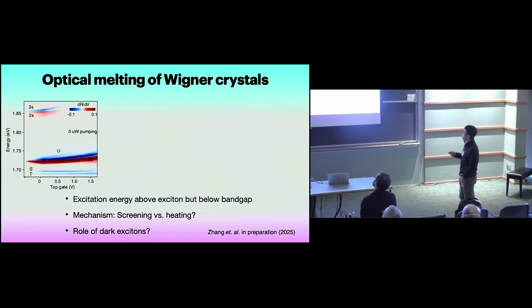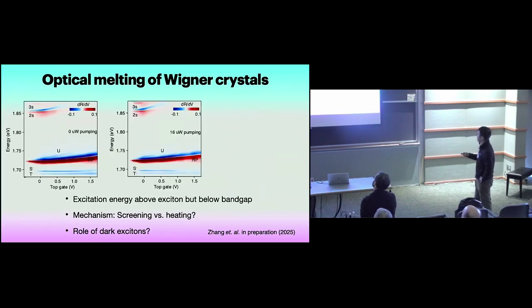So one thing that we can do is, in addition to this white light where we probe this Umklapp scattering, we can add another pump laser where it's above the exciton resonance but below the band gap, so that I create exciton population in addition to this electron population. If I do that and try to increase the pumping power, I see that with increasing pumping power, this repulsive polaron, this main feature, doesn't really change, but the Umklapp feature becomes much weaker. And eventually, it disappears.